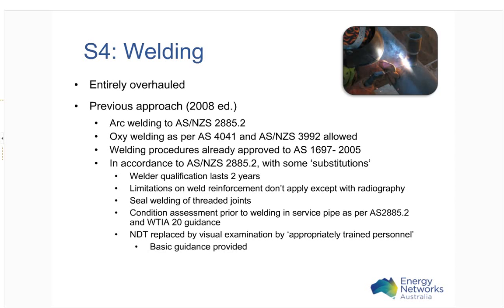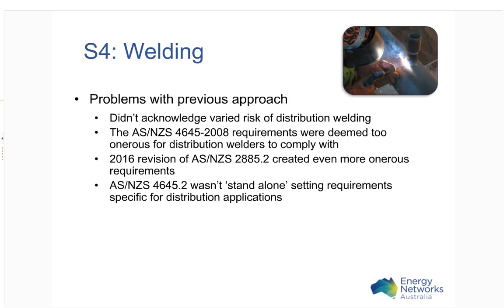So there were some issues that were identified with this previous approach. Firstly, it didn't acknowledge the varied risk of distribution welding. As all gas distribution operators would acknowledge, the risk associated with gas distribution assets varies greatly depending on the operating pressure, diameter, location. Welding ranges on distribution networks from low pressure welding or welding onto low pressure mains such as skinner tees for service connections, all the way up to large diameter, higher pressure welding on new assets.